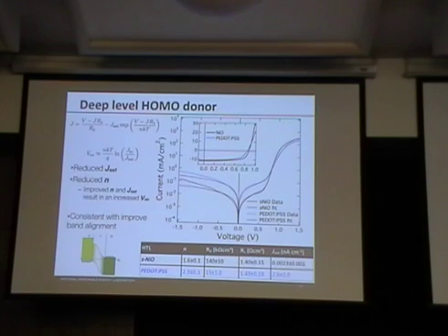If we look at the table, the resistance is different. In particular, the parallel resistance is very, very different, which means we have less net leakage through the device. Now, that's consistent with what I told you was the reason why we thought nickel oxide would be good, isn't it? Electron blocking? Yeah. Right? So that's a good sign that I haven't just fed you a line.